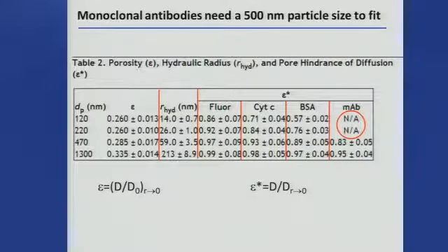And so when the particles are really tiny, they're very well behaved. You get a porosity that matches what is predicted for a face-centered cubic crystal. So around 200 or less, between 100 and 200, you just get really, really nice behavior. Pretty darn good behavior close to 500 nanometers, which is mostly what we're running with. And then as you get to bigger particles, the van der Waals forces between the particles are different compared to just RT, and so they just don't form quite as spontaneously. And so now if it were completely random, the porosity would be 0.4.